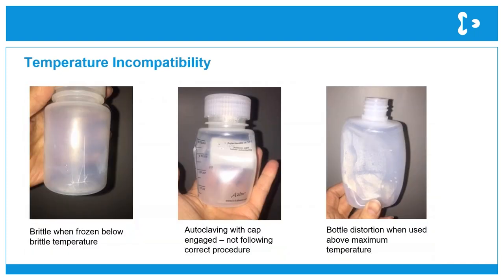As with chemical resistance, there are also implications to temperature incompatibility. Certain polymers that are not intended to freeze become brittle when taken below their brittle temperature. Here you can see when it's been dropped, it's cracked, and once it's cracked, it compromises any sample within the container. A lot of customer samples are either valuable or even hazardous, so protection of the sample is really paramount.